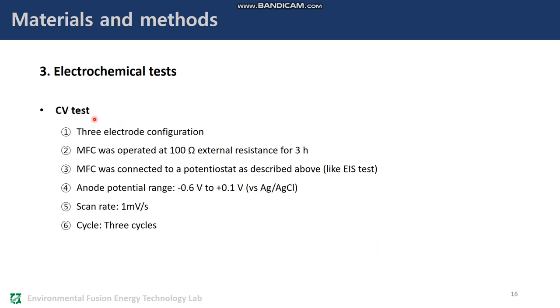Cyclic voltammetry. CV test for anode electrodes were carried out in a 3-electrode configuration. After medium change, the MFC was operated at 100 ohms external resistance for 3 hours as well. Then, the MFC was connected to a potentiostat as described in the EIS test, and then tests were performed. Anode potentials were scanned from -0.6 voltage to +0.1 voltage, with a scan rate of 1 mV per second to investigate the electrochemical activity of the anode biofilm. CV tests were performed in 3 cycles, and the final CV result was used for data analysis.